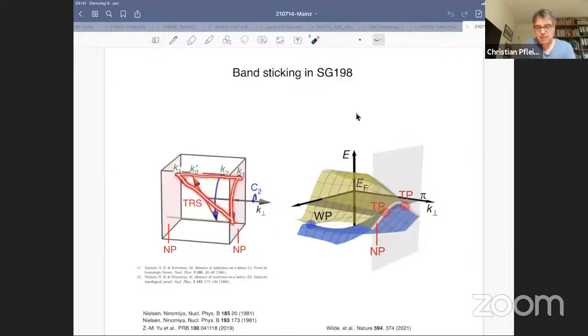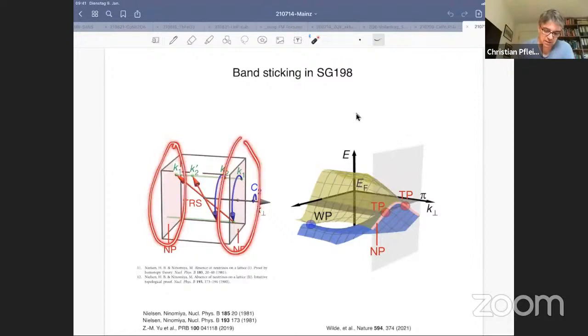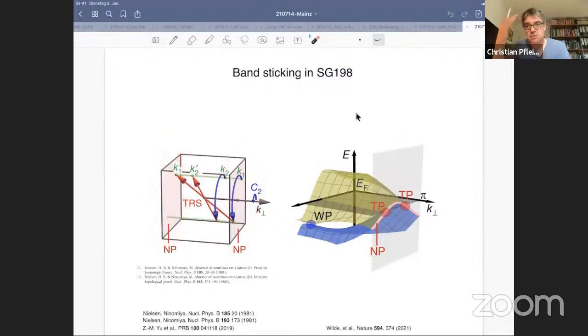operations, right, points, and you get degeneracies, you get a Kramers degeneracy, right? So that is something which applies to an entire plane, right? So you have these nodal planes, right? You have by crystal structure a mechanism which enforces degeneracies of bands, right? In fact, this applies not just to electronic band structures, but also to phonons or potentially magnons, right?